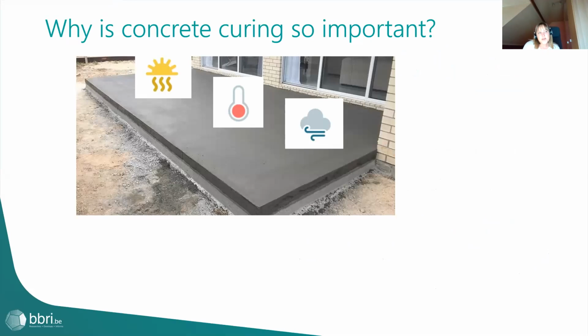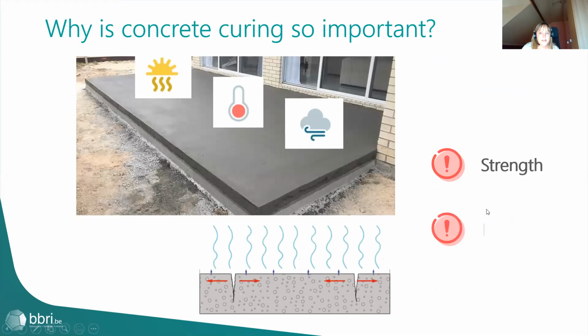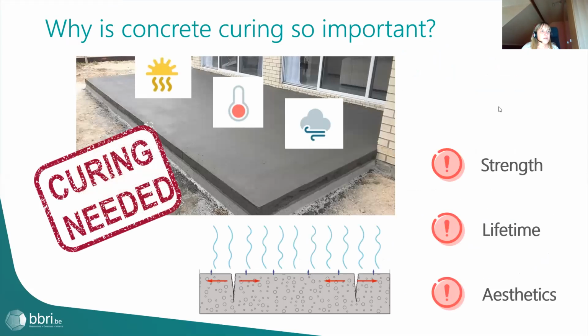First, a question: why is concrete curing so important? As you know, curing is the process of controlling moisture loss from fresh concrete. If no curing takes place, water will evaporate due to sun, wind, and hydration heat, so that not enough water will be available during the early hardening process. The consequences can be dramatic, such as bad strength development, cracking due to plastic shrinkage, thus reducing the lifetime of the concrete, and also bad appearance.